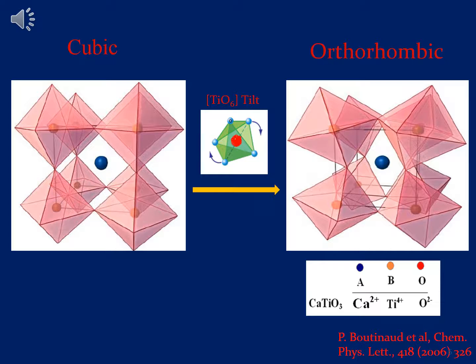Now, in the case when we excite the material, say using photons, electrons, or any other excitation source, then an electron will be shared between the A and the B ion. Now, due to the orbital overlapping that exists between the A and the B ion, this is interpreted as a charge transfer between the two ions, and it will exist in a state which is simply called an intervalence charge transfer state.